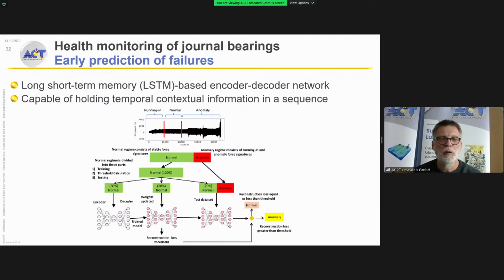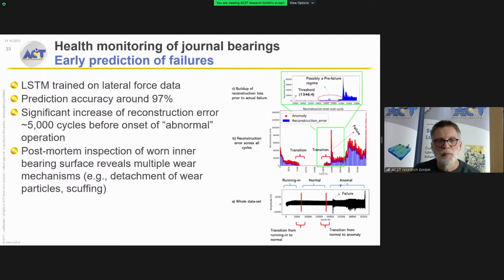So the goal here was how much before the anomaly actually starts we could detect a change in the signal. Again, we split the data into training and test data sets. That's always basically the same procedure. And what we could see here is that about 5,000 cycles before the force signal would actually indicate abnormal behavior, this algorithm could already predict, by a largely increased reconstruction error, that something is going to happen. And this, of course, is in my opinion the right tool if we would like to start investigating our system before it is damaged too much.